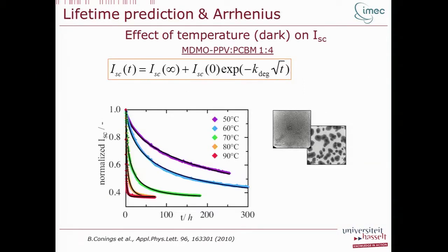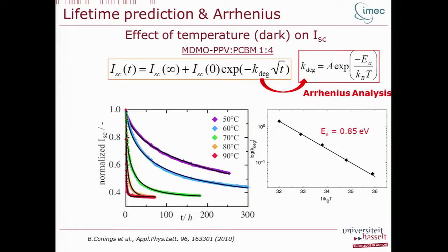So if we go to the a model system, MDMO-PPV:PCBM, where you see this kind of phase separation, what we've done is we looked at the short-circuit current at various temperatures, and we said this is an effect where PCBM moves, so it's a kind of diffusion effect. Diffusion is often described with the square root of t. It's a thermally activated effect, so we also bring in a k parameter that is related to temperature.